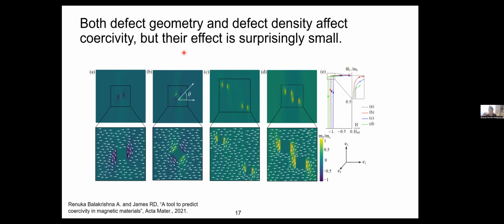And so we just did a test study where we changed, for example, the orientation of the defect, we changed the number of defects. We saw if we placed the defects close together. And the result was kind of surprising because what we noticed was, yes, the geometry of defects has subtle effects in which the magnetization reverses, and maybe especially if you zoom in, the curve of the shoulder of the hysteresis loop. But however, the effect was surprisingly small when compared to a more fundamental material constant. This was not as significant as it would be if I changed, for example, the combination of anisotropy and magnetostriction constants. And so this was a preliminary examination which kind of suggested that although defects may have effects, they are surprisingly quite small, and the material constants are playing a more dominant role in this magnetization reversal.